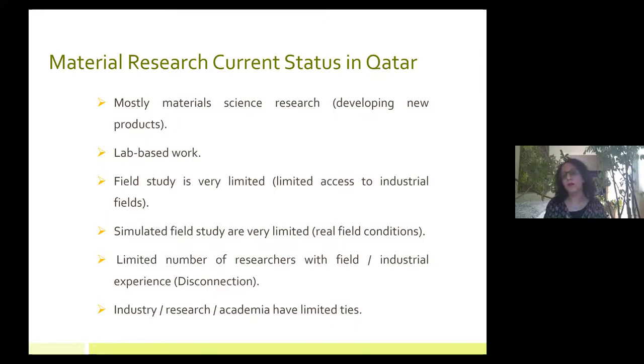I'm going to give an example of this. I've been working for the past, let's say, 8 years on chloride stress corrosion cracking. My area of interest is environmentally assisted cracking, and this is one of them. And so I've been doing this work in the lab to simulate the field conditions. And normally, when people do chloride stress corrosion cracking, the common test we use is called the slow strain rate test.